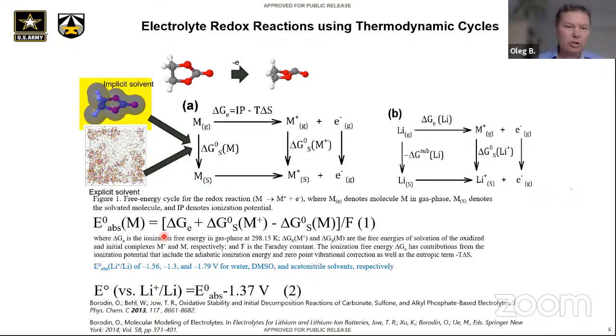However, that will give us the absolute electrode potential in vacuum. So on an absolute electrode potential scale, essentially, instead of doing exact calculation, which is very hard if we have explicit solvent, meaning that we take molecular dynamics simulations in which we put a couple thousand atoms inside of the box and solve Newton's equation of motion and sample the phase space, all possible configurations. It's hard to calculate. You need some reactivity, right? So it would have to be represented using DFT at least, in order to handle the oxidation problem coupled with the solvation problem. So typically it's done in much simpler ways, where we can calculate solvation energy for the neutral molecule, solvation energy for the cation, and ionization potential, free energy, what it takes to oxidize the molecule in the gas phase. Right?